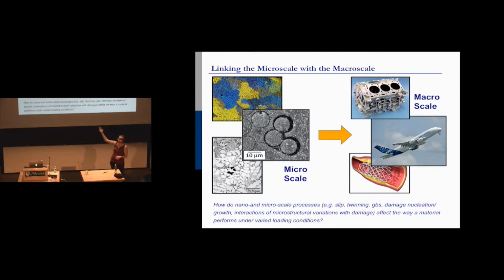These materials are flying now. They've just started flying. There's a tremendous amount of research investment in these materials right now. And the interesting thing is you actually want these materials to crack. But you want to prevent the bad cracking. You want to prevent the cracking that's going to lead to final catastrophic failure. So you want little micro cracks that basically start, dissipate energy, and then they stop, right? And you want them to be pretty uniformly distributed. So you want to actually control the cracking.